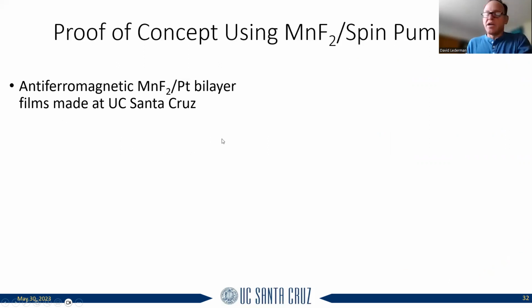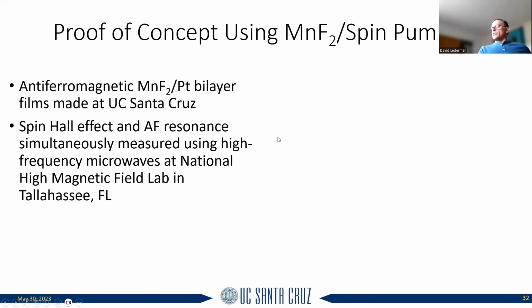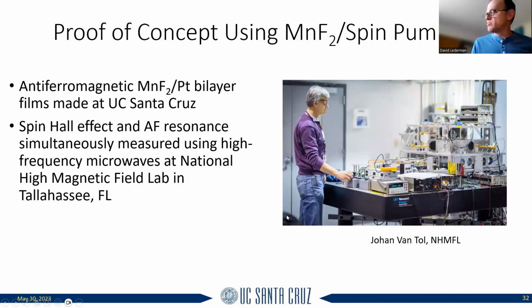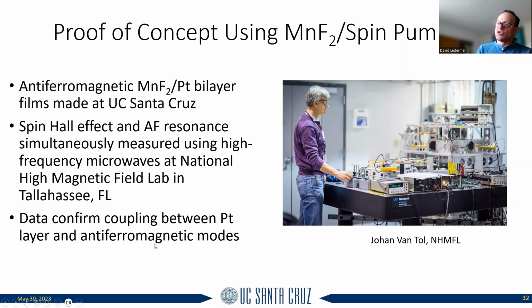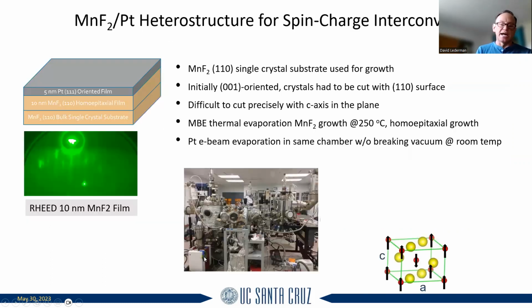So I want to show you what we did to prove that this is possible. We did some work in collaboration with the National High Magnetic Field Lab in Tallahassee, Florida, where they have a tunable high frequency microwave source. It's almost in the terahertz range, several hundred gigahertz. Basically, the experiment data confirm that we are coupling between the platinum layer and the antiferromagnetic mode. So I'm going to show you that this spin pumping mechanism actually works.